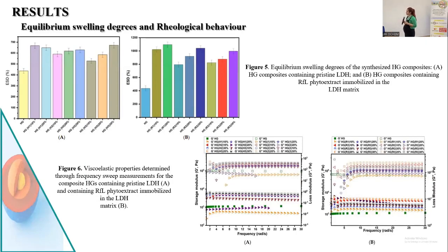The equilibrium swelling degrees and the rheological behavior. The equilibrium swelling degree, the swelling ratio, increases with the addition of the LDH. With the increasing of the LDH, we can observe also an increase in the swelling degree, and also an increase with the addition of the phytoextract inside the LDH.